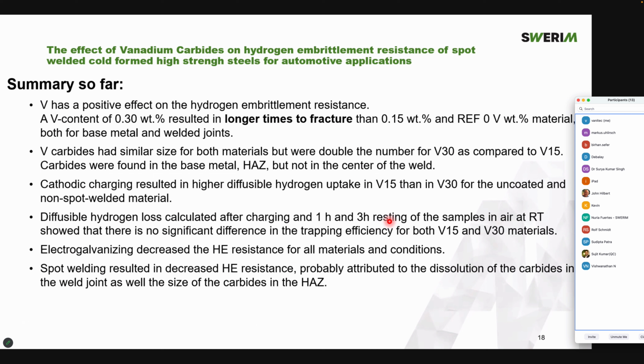Then we calculated the loss of diffusible hydrogen after 1 hour and 3 hours resting the samples at air, and there was a similar trapping efficiency for the 0.15 and 0.30% materials.